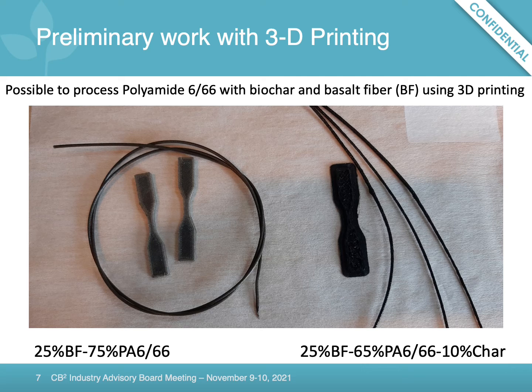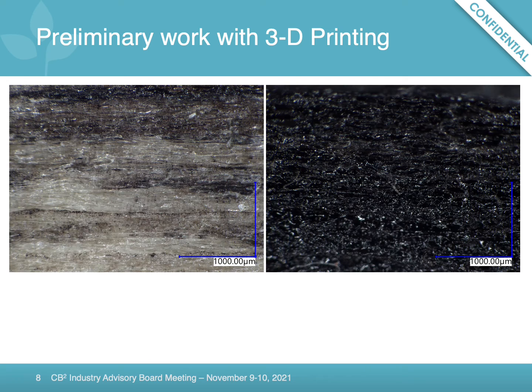The figure here shows filaments as well as specimens, tensile coupons, that were produced using the two formulations. Both these formulations included basalt fiber and polyamide, but the formulation on the right also included 10% biochar, whereas the formulation on the left did not have any biochar. We examined the specimens that were produced using optical microscopy and found that the blends that had biochar included in it, like the one on the right, had a natural black pigmentation to it.